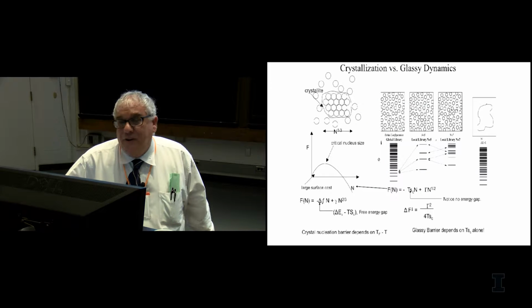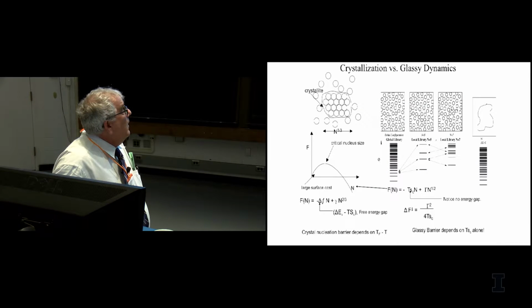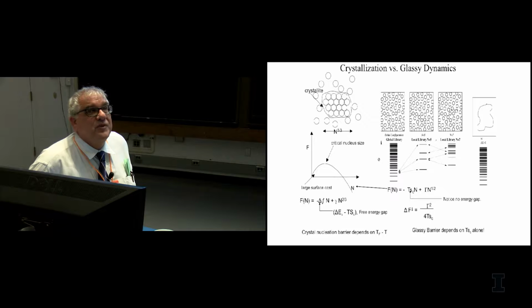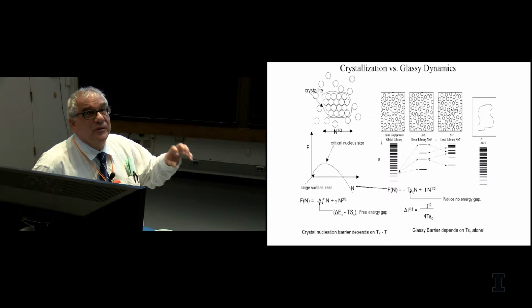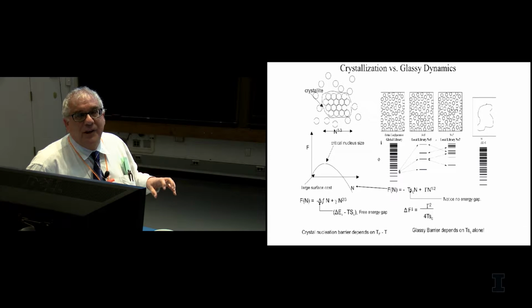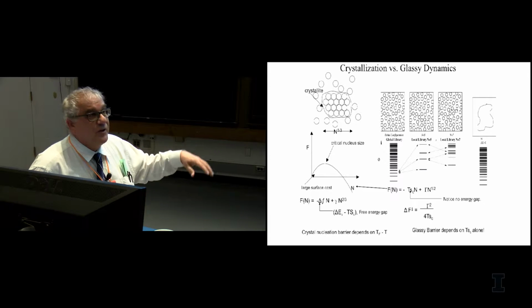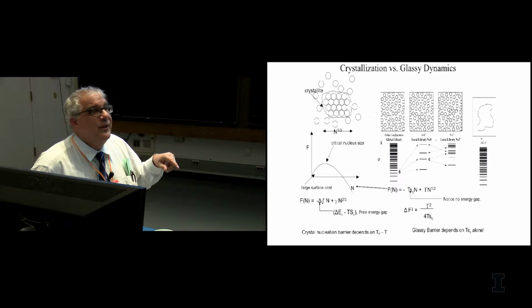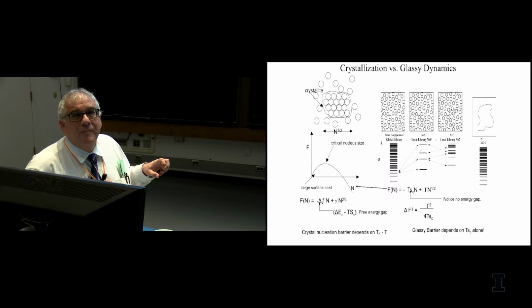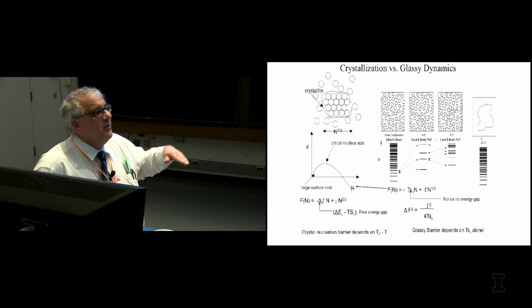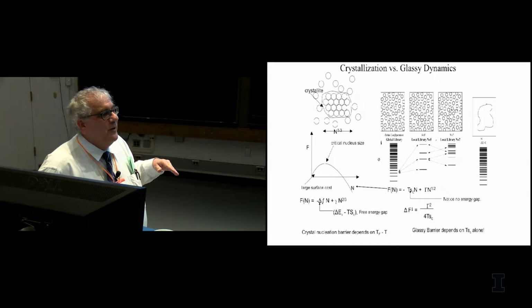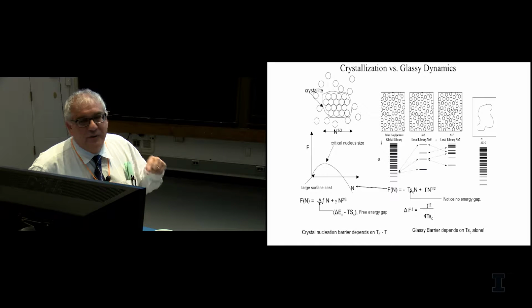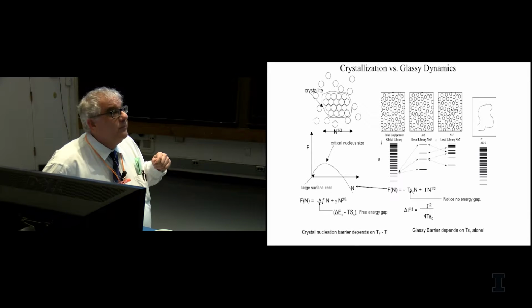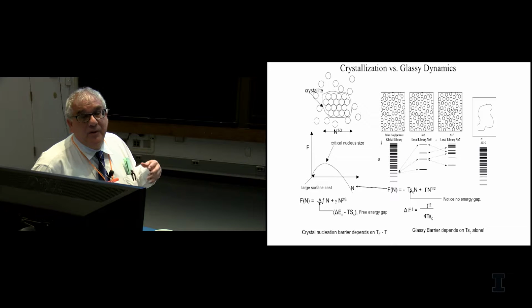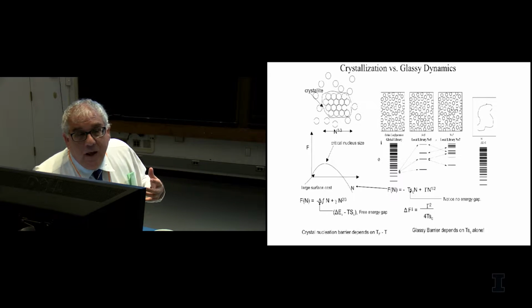Now, how do you move at all in this temperature regime? Well, if we had a single crystal changing to another crystal, we would develop a nucleation theory. We would take a certain structure, we would cut a little bit of it out, we would stick in the other crystal structure. Within the crystal structure, the energy would be somewhat different from where you started. And then, of course, at the border of the region that you cut out, there will be a mismatch. The energy will be higher. There will be some kind of surface energy.